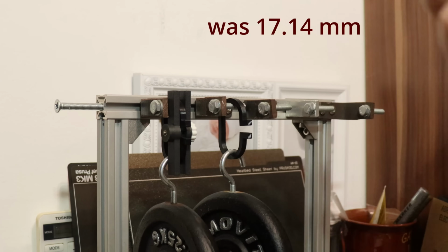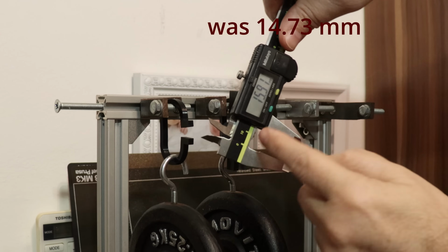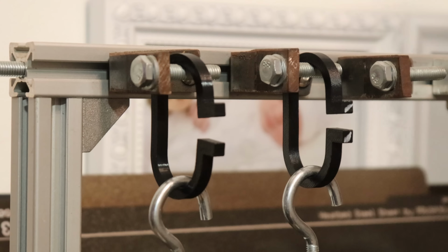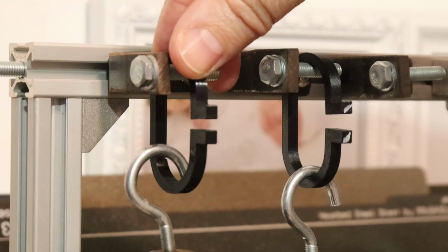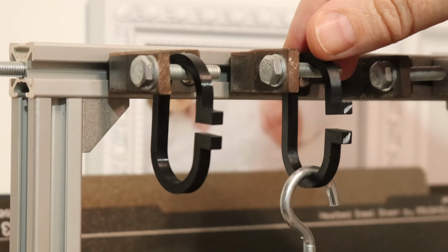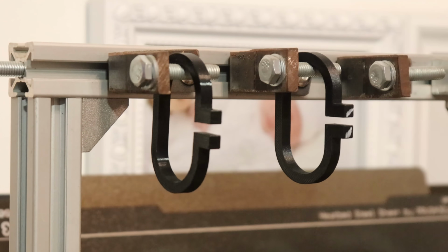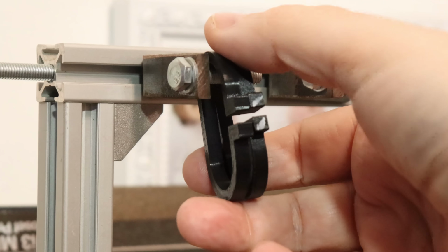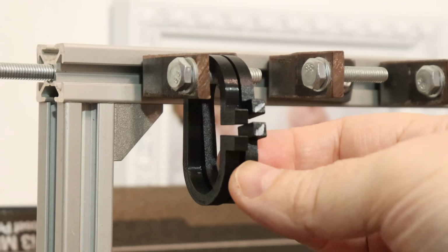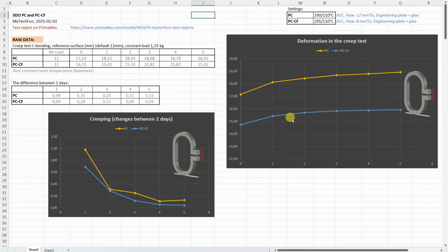18.92, 15.91. Let's remove the load. There is a permanent deformation on both of them, but less on the carbon fiber version. So the PCCF had a smaller deformation, but what we need for the creeping is the difference between 2 days. And even here the PCCF was better, but in both cases I could record some creeping in the first 3 days. Only after the 4th day it became negligible.